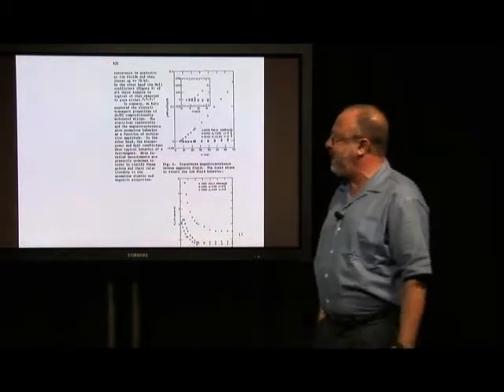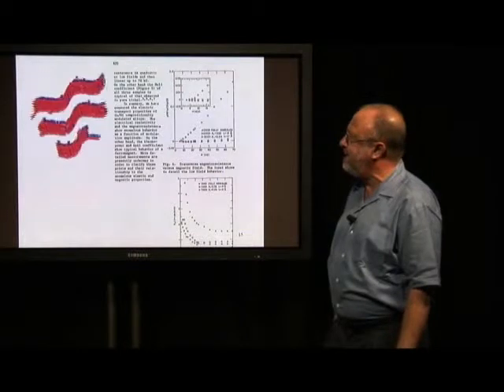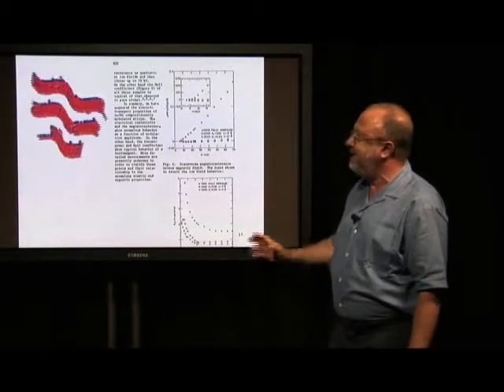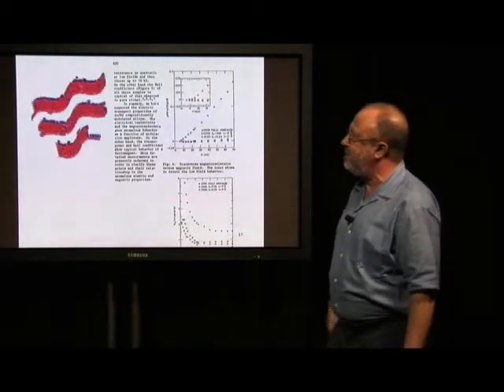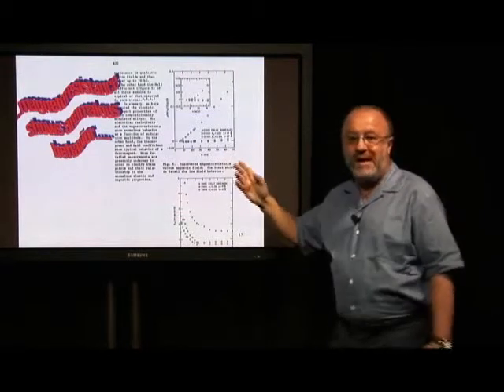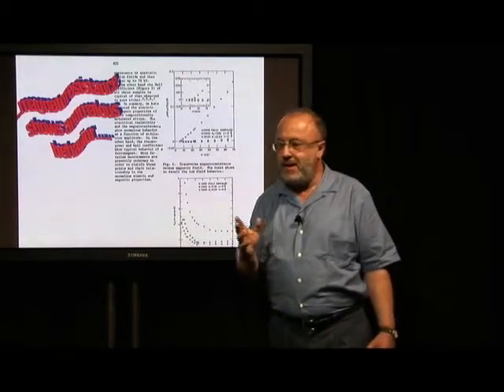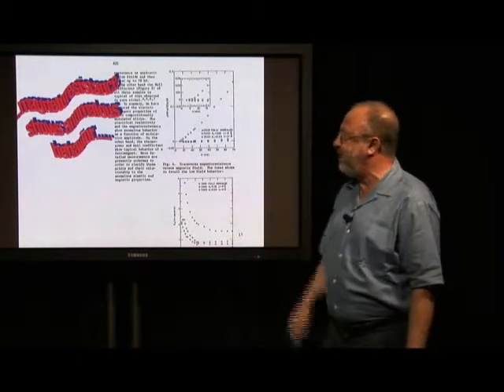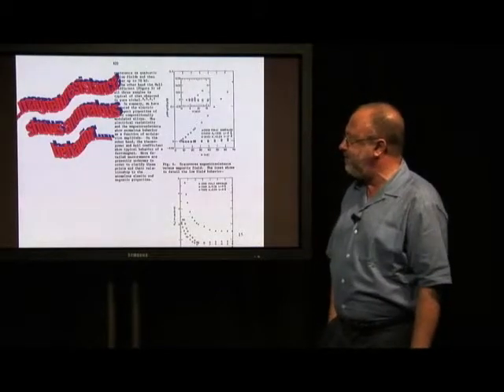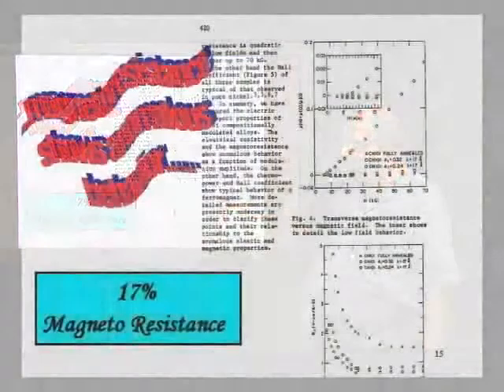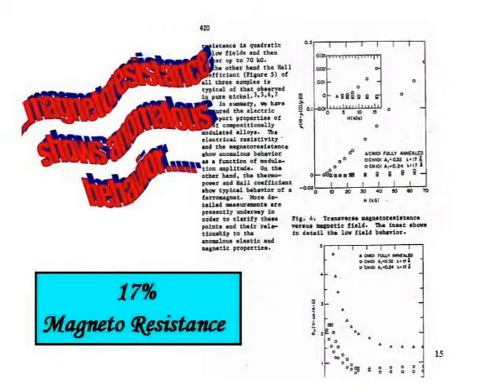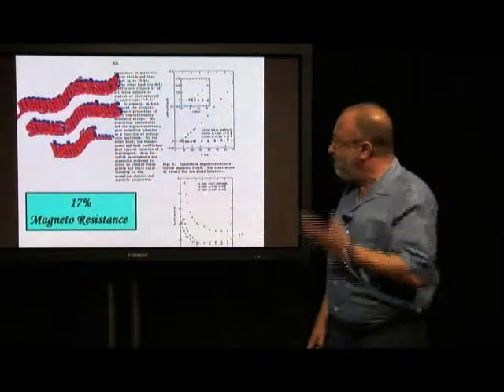of these metallic superlattices, and what we found in these metallic superlattices was that the magnetoresistance shows an anomalous behavior. Now this anomalous behavior was the fact that we found a very large magnetoresistance of about 17%, while typically for metals the magnetoresistance is less than 1 or 2%. So this was kind of a major thing, that the magnetoresistance was so large.